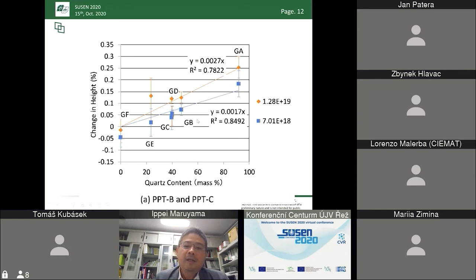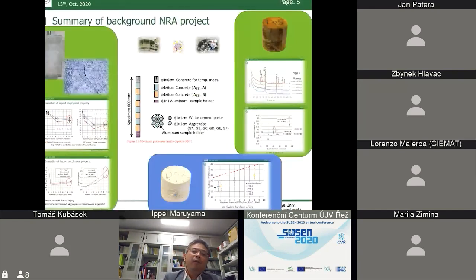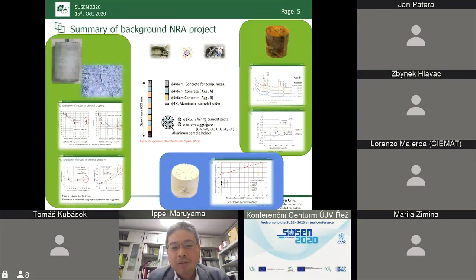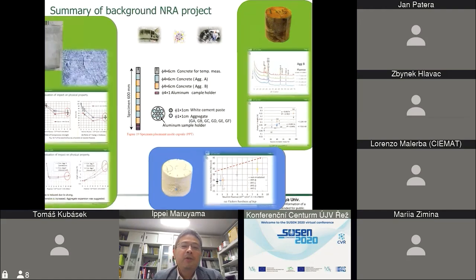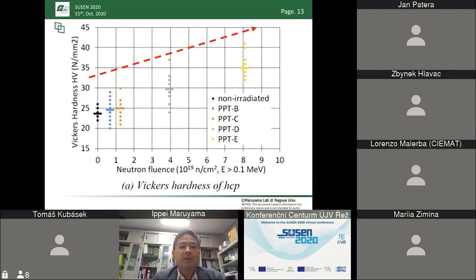So when we think about the concrete, the binder is the cement paste. It's a mixture of cement, or Portland cement, and water. And when we did the irradiation, we confirmed the strength change by using the Vickers hardness evaluation. So this is a relationship between the Vickers hardness and the neutron fluence. And as you see, we see an increase in the strength of the hardened cement paste after the irradiation. So it means that the cement paste is very durable, tolerant to the neutron irradiation.